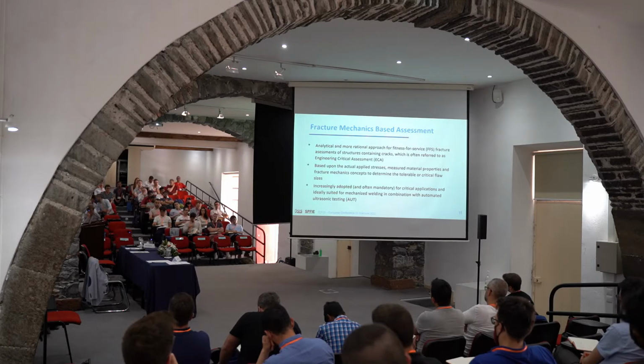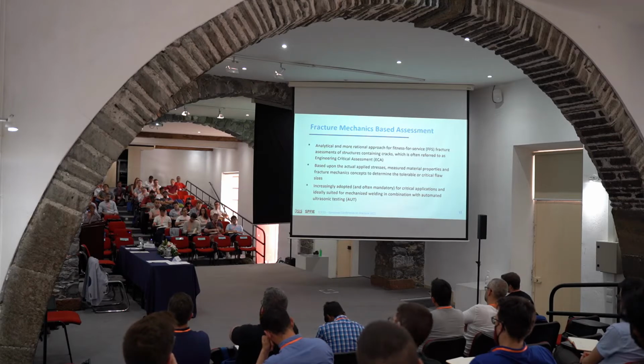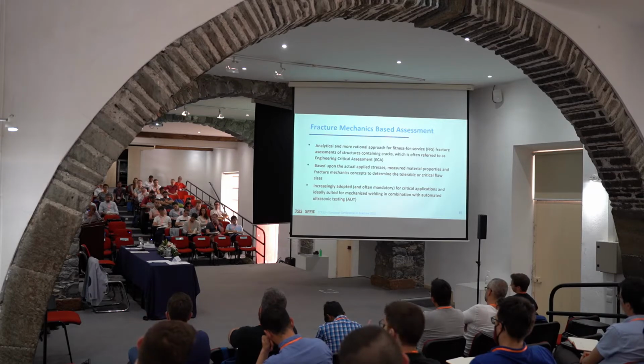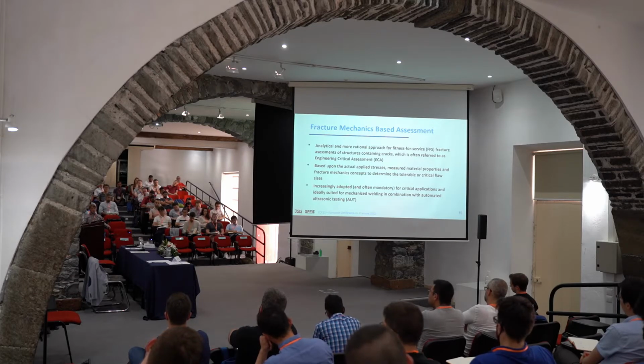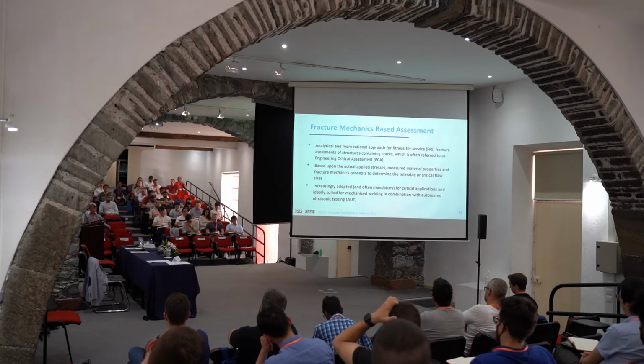Okay, that's the idea. Remember that the workmanship standard or criteria, the philosophy behind it was this: if you find anything that looks like a flaw, discontinuity or something like that, you just repair it. Using the ECA philosophy, even if there is a flaw in your structure, you analyze it using fracture mechanics and say, okay, this flaw can stay here. I do not need to repair it because it's not critical.